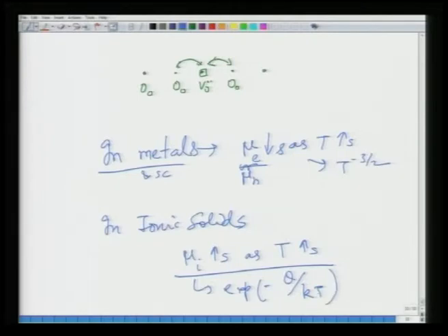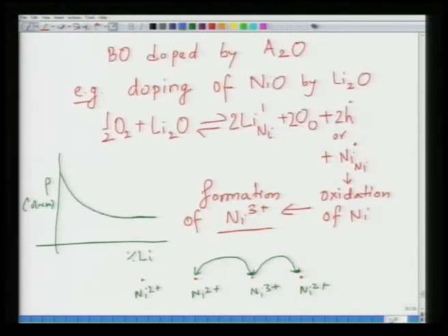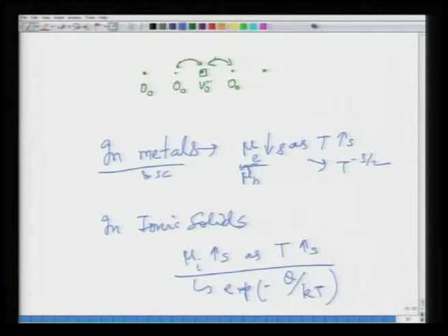So, this basically you can imagine as if you have counter movement of vacancies, because a charge is associated with the vacancy. In the previous case you can say it is the movement of Ni3+ ions. In this case it would be a movement of vacancies. So, instead of charge transport you must consider this rather as an ionic transport. So, that is why conduction in ionic systems is a hopping kind of system, because here the defects move, and movement of defects is nothing but diffusion.